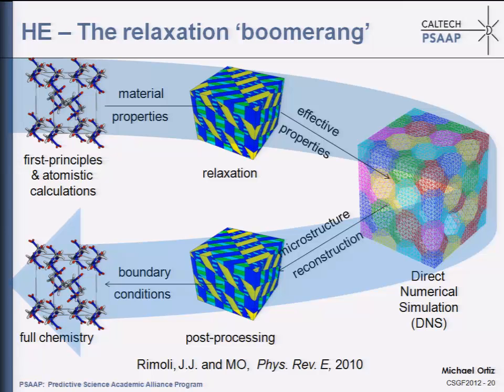So this is supposed to be a material point, a representative material volume, okay, that in a macroscopic simulation would sit somewhere within the mesh. And these are the typical microstructures, the optimal microstructures that give you the effective behavior of the material. These are called sequential laminates. You can show mathematically that it is precisely these microstructures that give the softest possible response of the material. So these are the optimal microstructures. And we can generate them analytically in closed form, and we can get the effective behavior analytically in closed form. That's great news. Anytime you can avoid doing calculations, that's great, because having solutions analytically in closed form really saves you huge amounts of calculation.